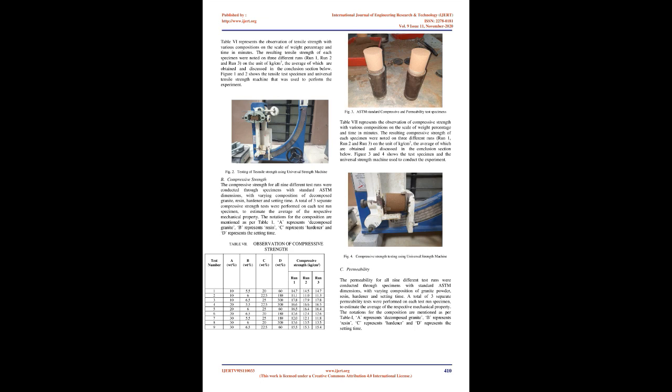To check the properties of the mold sand mixed with the decomposed granite, an analysis of compressive strength, tensile strength and permeability was conducted. Specimens were made compatible for testing these respective properties. Test number 1 represents level 1 composition of decomposed granite of 10 WT%, 1.8 WT% resin, 20 WT% hardener, and a setting time of 60 minutes. Test number 2 represents level 1 composition of decomposed granite of 10 WT%, level 2 composition of resin with 2 WT%, level 2 composition of hardener with 22.5 WT%, and level 2 setting time of 180 minutes. Similarly, further test runs were made with varying levels of composition of decomposed granite, resin, hardener and setting time.